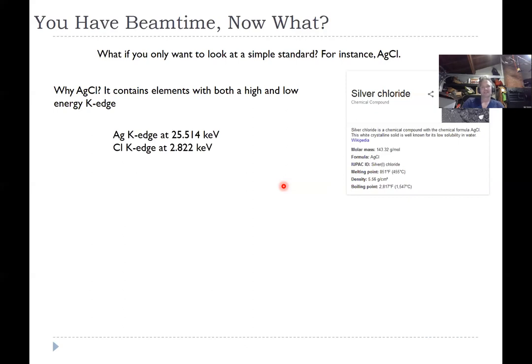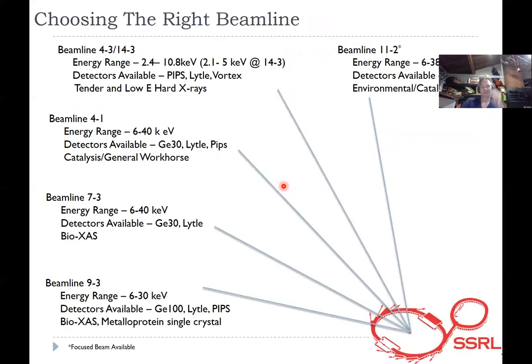So the silver K-edge is at 25 keV and the chlorine K-edge is at 2.8 keV. So an order of magnitude difference, which puts you in two completely different experimental regimes in terms of sample preparation and how you'll collect it. You'll probably need two beamlines. If you look at what beamlines are suitable, you can look at 4.1. Most of the hard X-ray beamlines will collect the silver K-edge. But only 4.3 or 14.3 are capable of doing the chlorine.